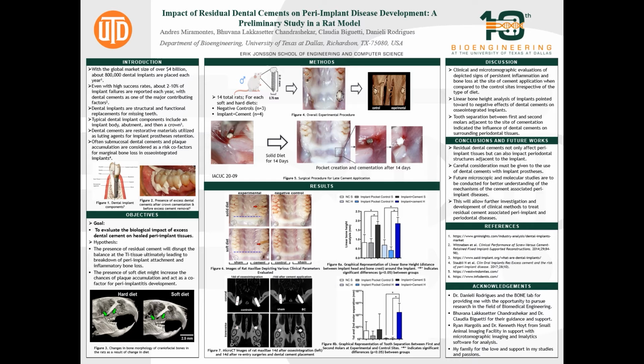The major takeaways from this analysis are that linear bone height implant data expresses the negative effects of dental cements on osseo-integrated implants, while the tooth separation of the first and second molars that are adjacent to the cementation site indicate the influence that dental cements have on surrounding periodontal tissues. To conclude, residual cements not only affect peri-implant tissues but can also impact periodontal structures adjacent to the implant. So we must take careful consideration to the use of dental cements with implant prosthesis.